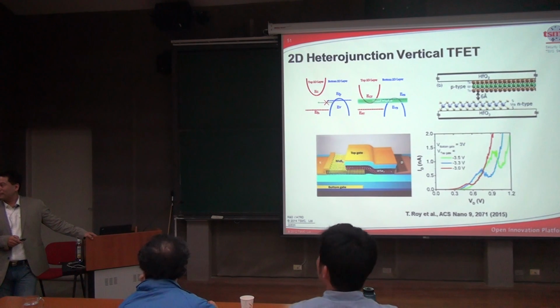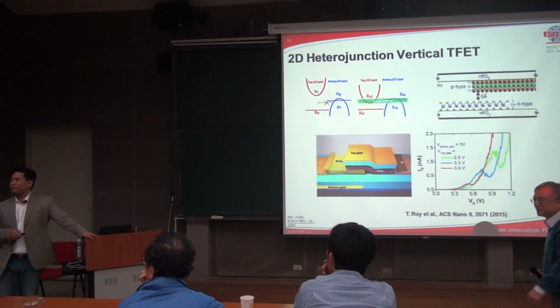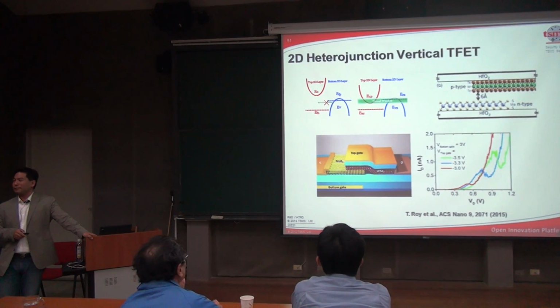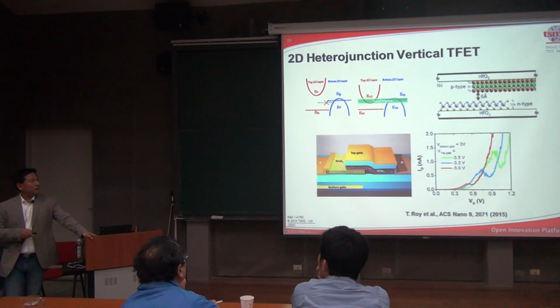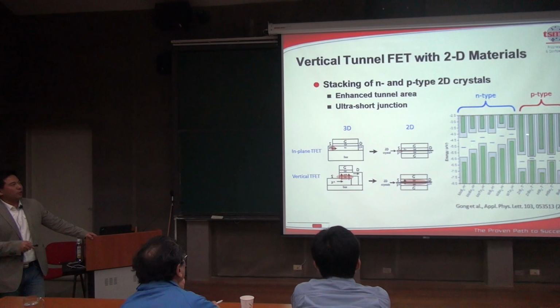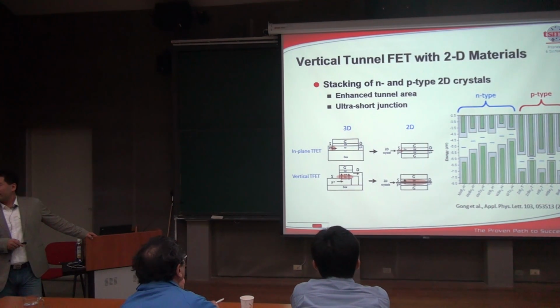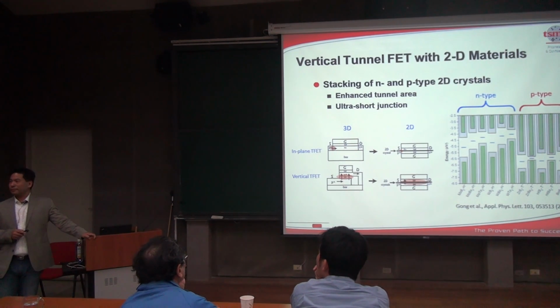So I follow this question. What's the tunneling barrier? For a planar device, the tunneling barrier normally is the bandgap. Yes. For this one, what's the tunneling bandgap? That's related to the band alignment of the material. So you have a vacuum. You have a vacuum, there's not two materials, there's a vacuum in between. Right. So the barrier height should be different from the planar.